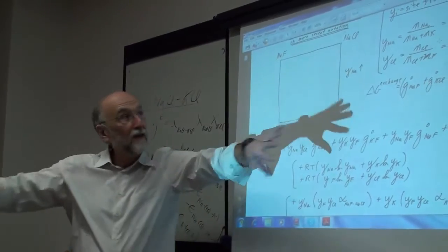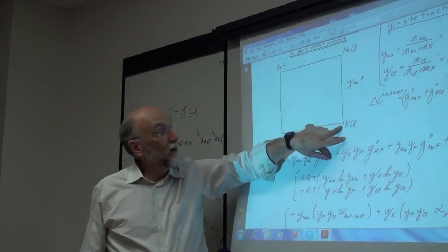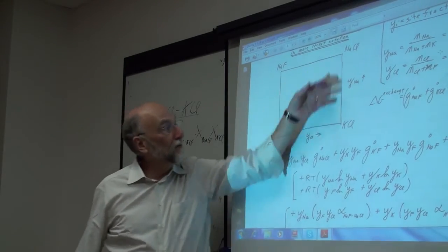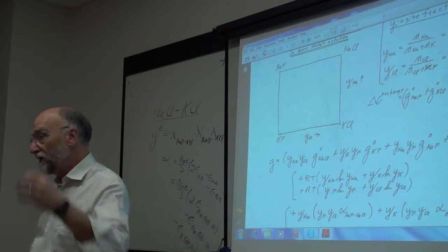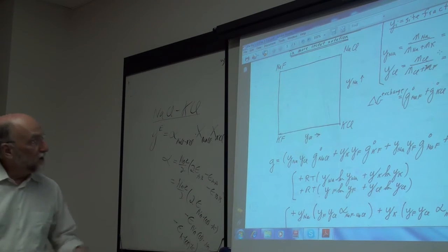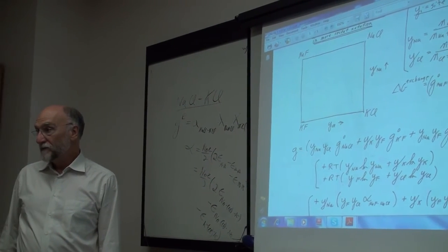Just forget the chlorine lattice. Look only at the sodium-potassium sublattice, and it's a one sublattice model. The chlorine sublattice just goes along for the ride, and the sodium and potassium are mixing randomly on the cation lattice as a regular solution. And the bond energies we're talking about then are the second nearest neighbor bonds.